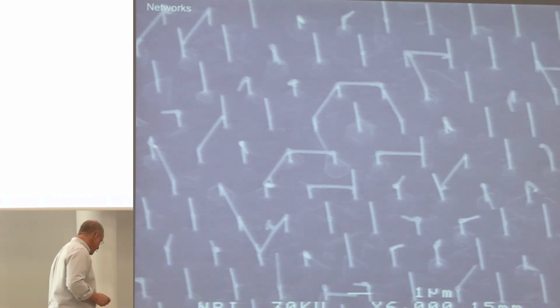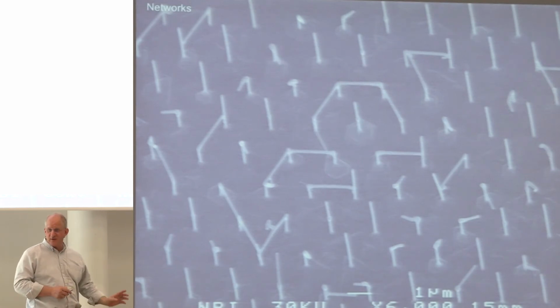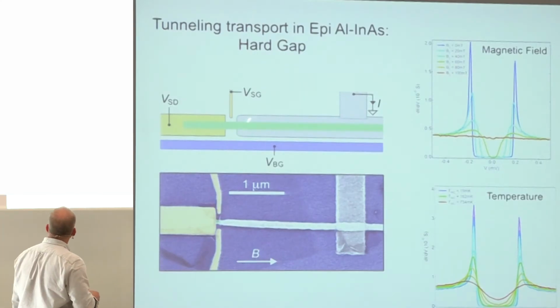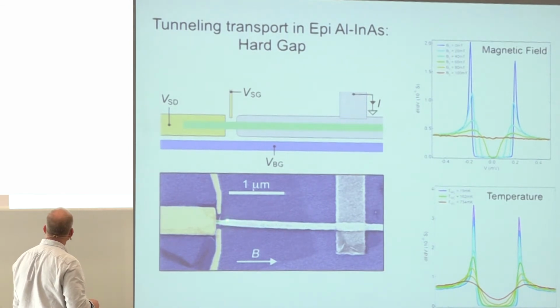It's pretty remarkable. I would think that if you didn't know me and I was just telling you this, like, at a bar or something, you can grow them, you go sideways and it hits the other guy and then they grow epitaxial, you would just think I was crazy. But when you do it, here's a case where the MBE system was rotated during the growth of the aluminum, so the aluminum goes all the way around it, but you'll see that that doesn't matter as we continue.